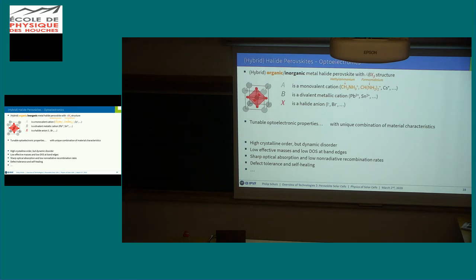It's a paper in Advanced Materials by David Egger, who really captures what is currently the research focus for perovskite material science. One thing on the top is that they exhibit a very high crystalline order. This is the lead sublattice that gives very sharp Bragg peaks, whereas you have dynamic disorder on the halide sublattice.